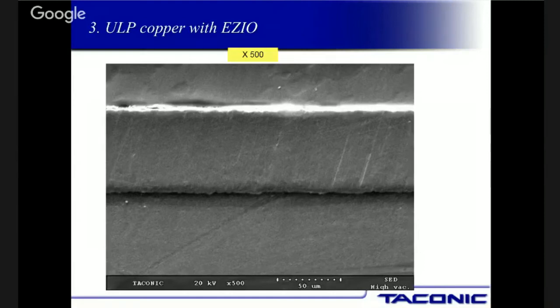And so that's the issue: what happens as the boards are getting more dense? Traces are getting closer together. In the microwave industry, we call it high frequency shorts. You build a board and you have DC, nothing shorts out, but you put RF energy to it and you get these high frequency shorts in the board because the fields make it look like a short. And why is that? Well, there could be growth from the plating, the copper could be oxidizing, or the etching chemistries still stay on the board, and over time they wick through the material, either along the glass bundles or around the ceramic particles or the different fillers used in the material, and 3 months from now you get shorts in the board because the chemistry has wicked across.